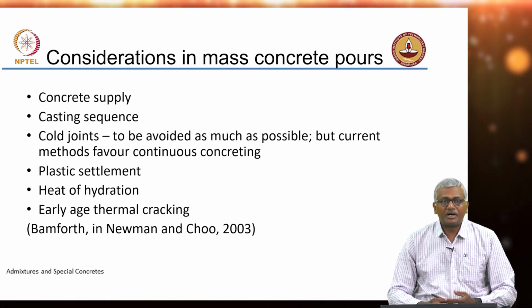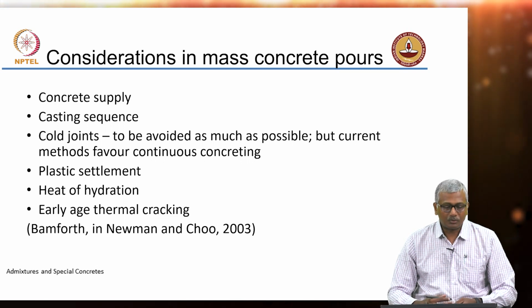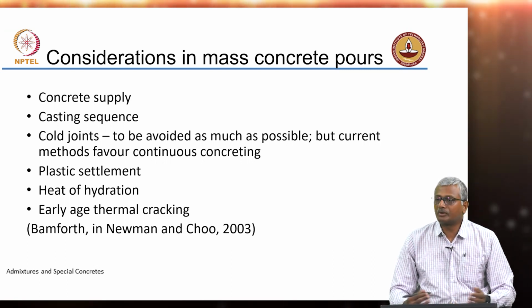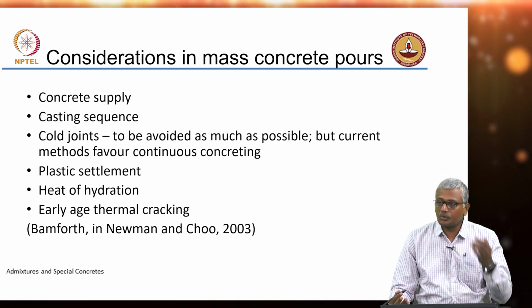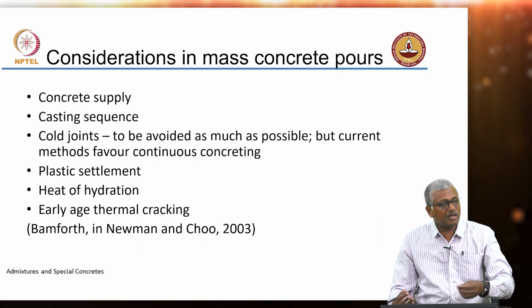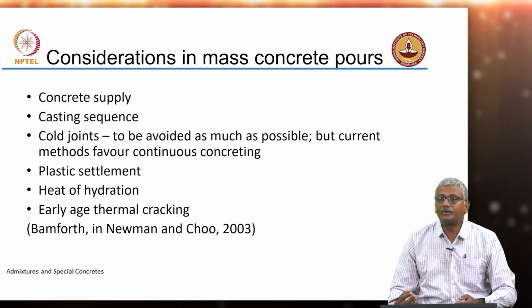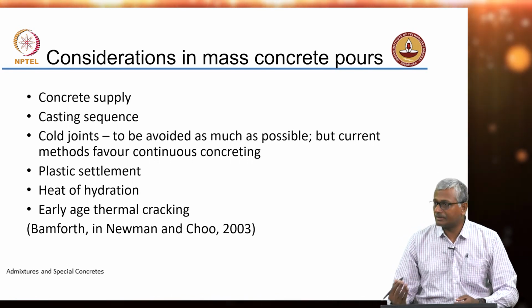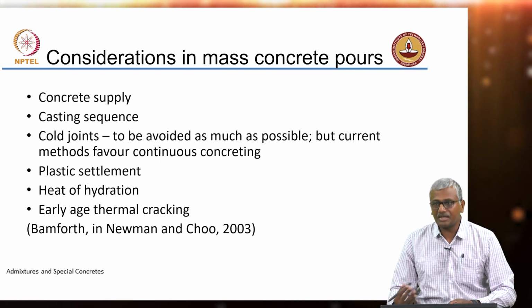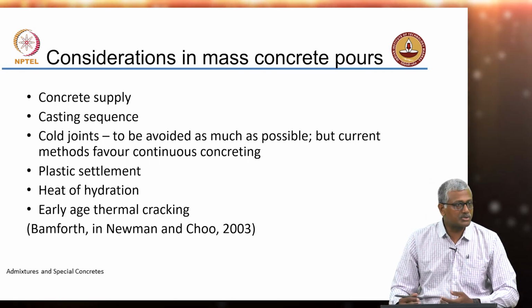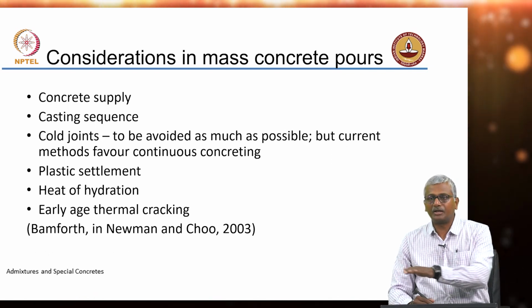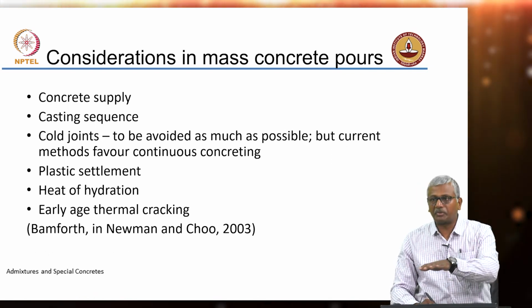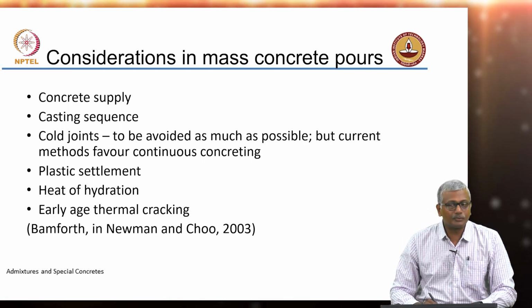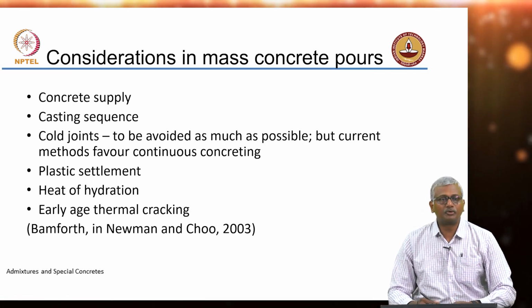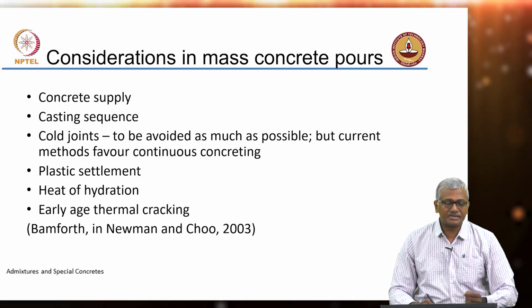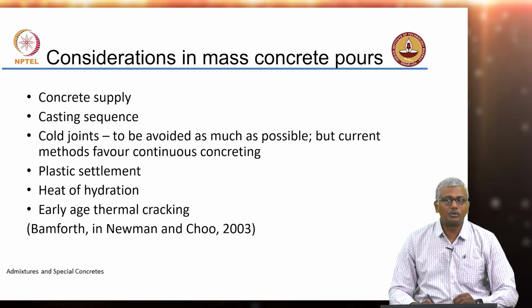Now, in mass concrete pours, there are several things to look at. One is concrete supply, because you are casting a massive structure. So, you need to ensure that the concrete supply is continuous to be able to continuously cast it. You need to also ensure that you have clearly worked out the casting sequence with which you are pouring the concrete. Where do you start? How do you move? Do you move from one end to the other, or do you complete the entire thing together and then move up? All of those things are required to be decided before the concrete is placed, because all of this is necessary to avoid cold joints. You need to avoid cold joints as much as possible.